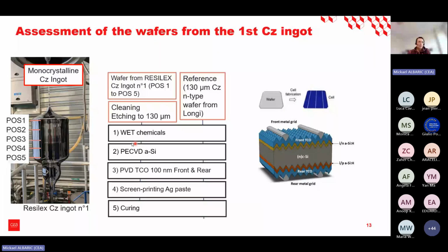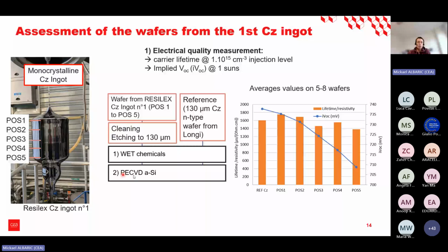So here are the ingots. The wafers we used for this experiment are from the top to the bottom of the body of the ingot, where the wafers have been manufactured. So position 1 to position 5. Here, this is a typical heterojunction cell process we used. And here, this is a picture of the symmetrical layers of these cells. And what we did after step 2, so after the deposition of amorphous silicon layers, we were able to monitor the carrier lifetime at 10^15 per cubic centimeter injection level, and we were also able to measure the implied VOC.